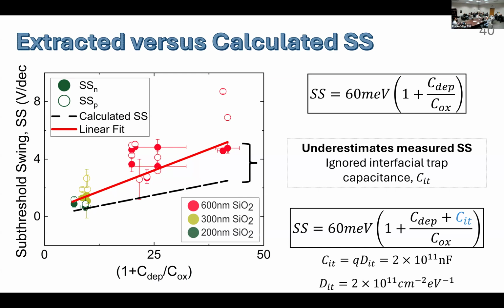So physically, this arises from the fact that the oxides that we use are not made perfectly. They have some kinds of impurities inside of them that will introduce traps. These impurities are either positive or negative, and their ultimate sum will result in this interfacial trap capacitance. If we add this additional parameter to our fit, we can extrapolate values for the interfacial trap capacitance, which align with the range of values that we see for tungsten diselenide on oxide dielectrics.